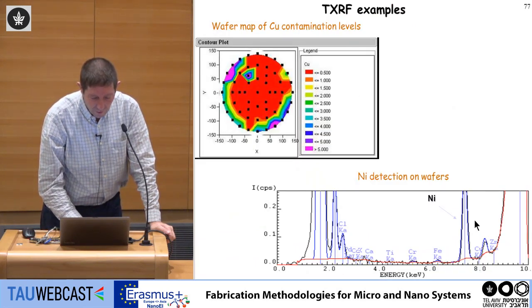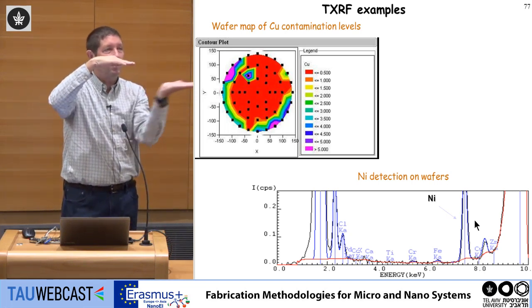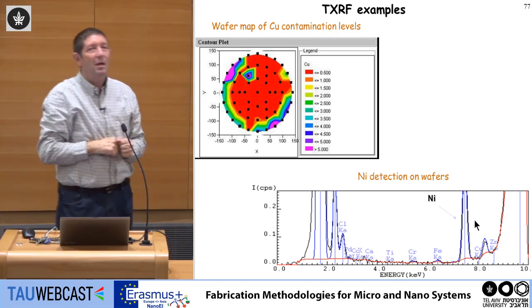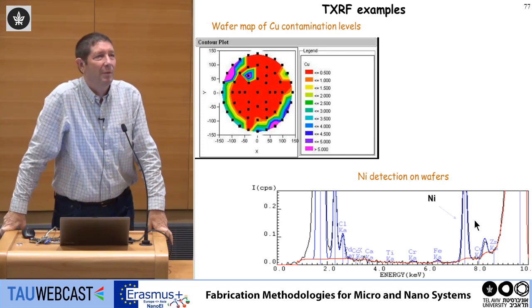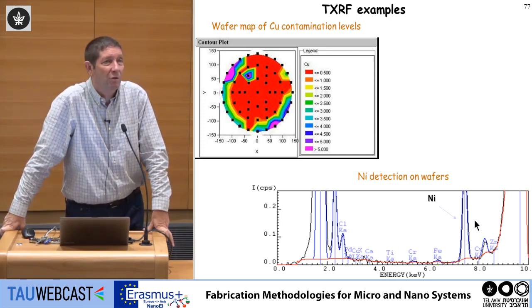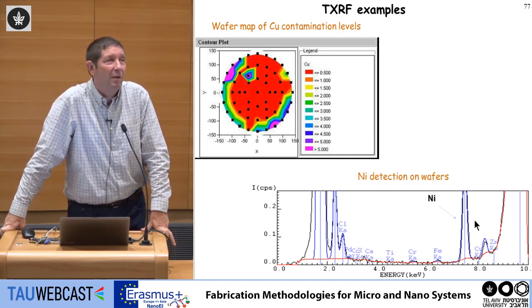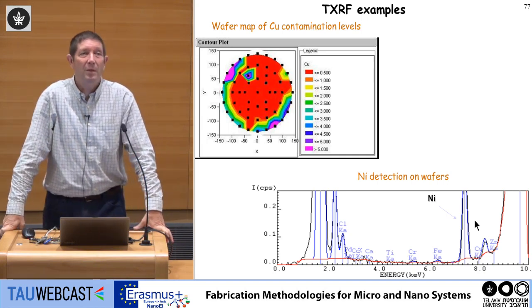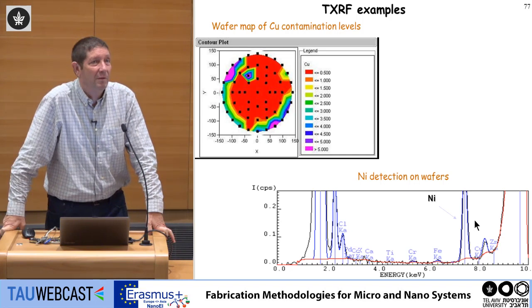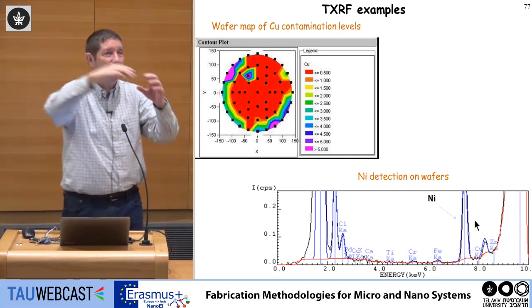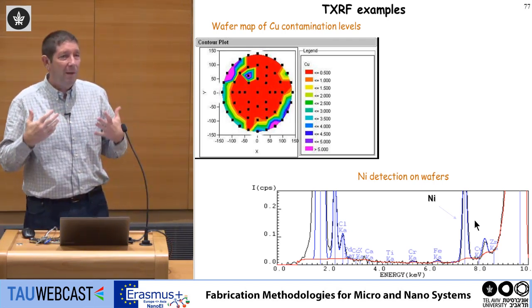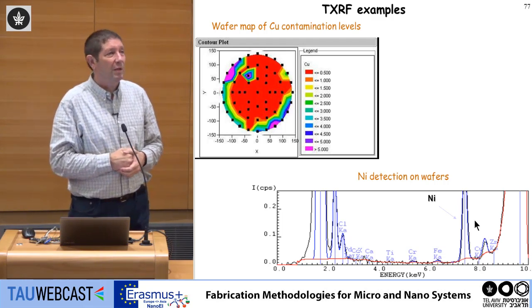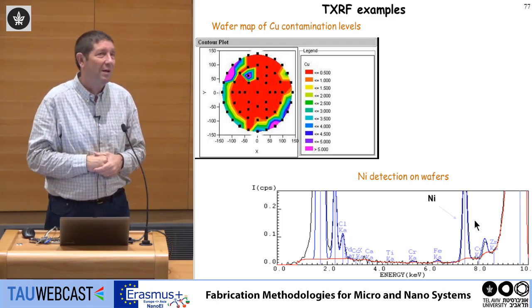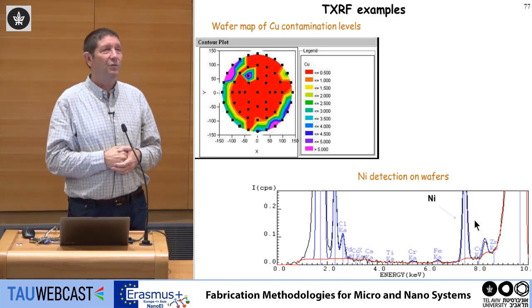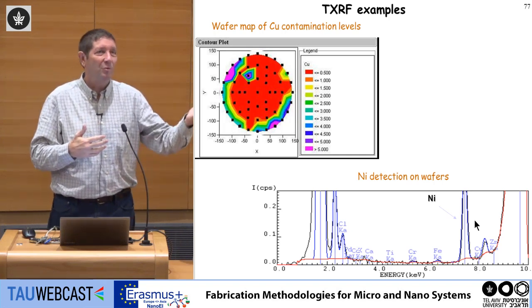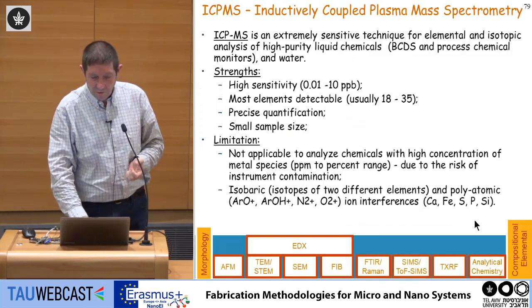No animation here. You can do the measurement and rotate the wafer, and you can actually get a mapping of contamination. Because it's extremely sensitive, and one of the biggest problems in the semiconductor industry, or in nanotechnology and microtechnology at large, is metal contamination. The reason is that during manufacturing, when you make devices, you use a lot of metals like tweezers, and gases are coming through metal lines, and metals, when they penetrate silicon, can cause a lot of damage. So you need very high sensitivity methods to measure metals on surfaces, and the other option is to do post-mortem on your samples, but you don't want to do that. This is the TXRF method.